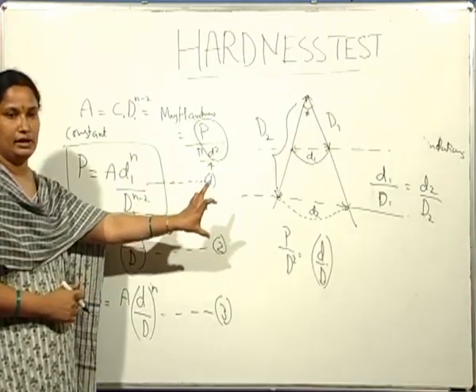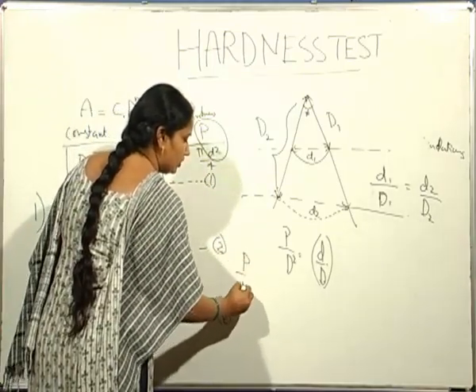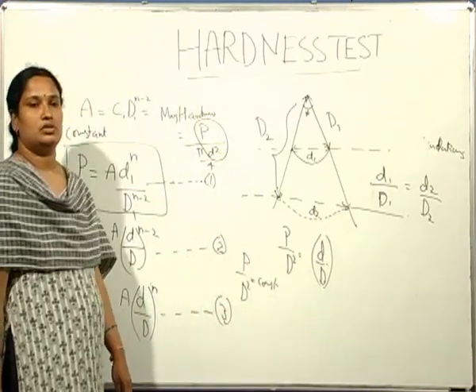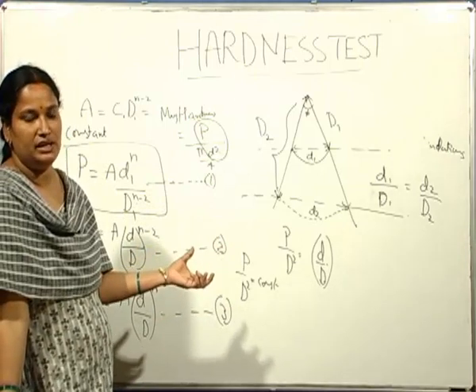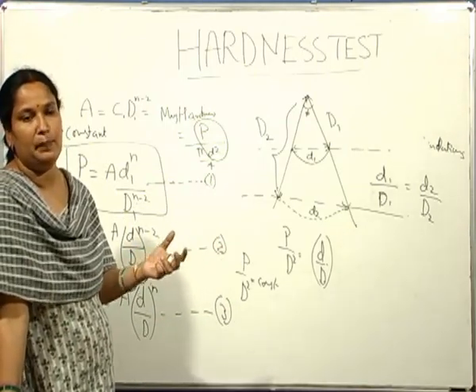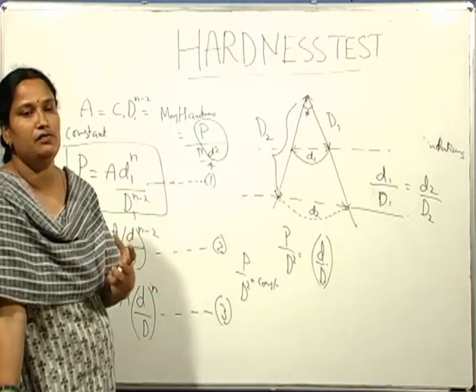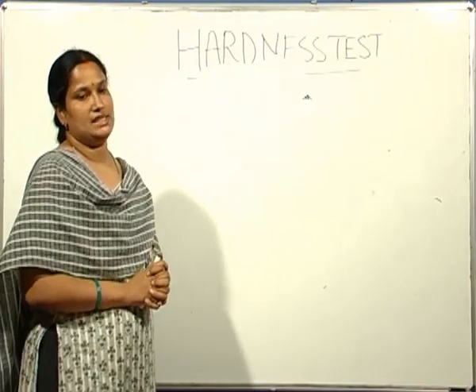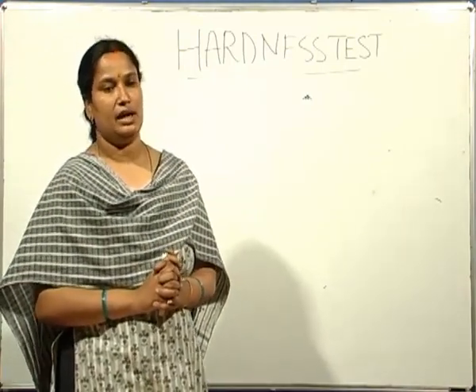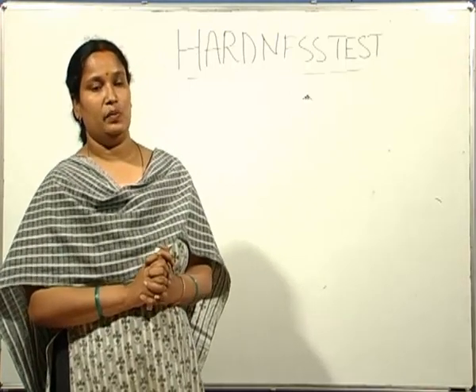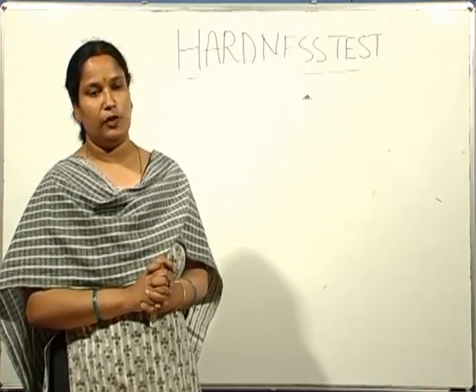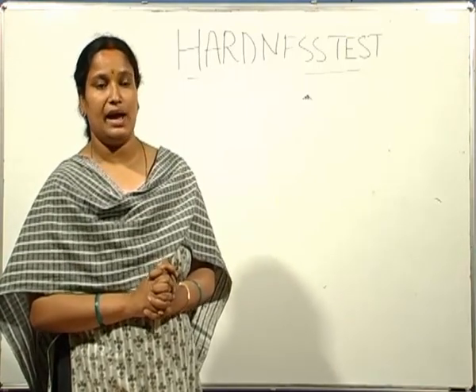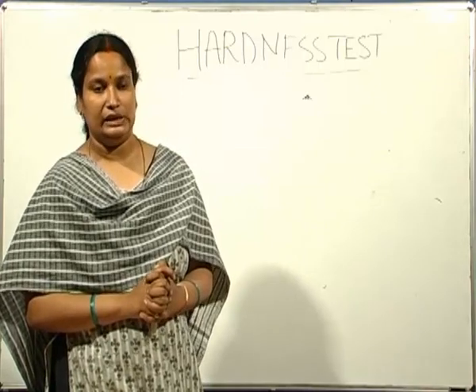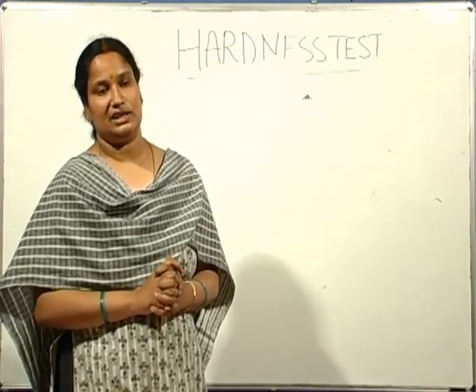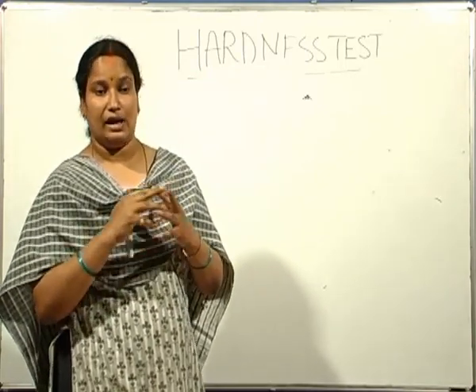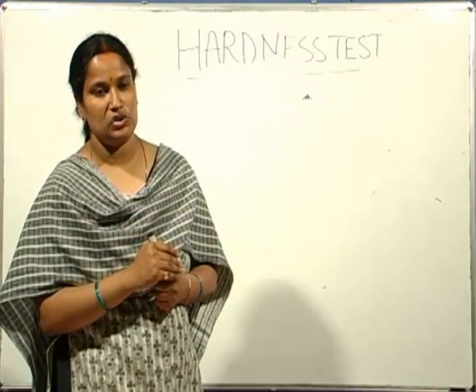So as long as the ratio P by D square is maintained constant, geometrically similar indentations are obtained and the hardness does not depend upon load. It does not vary with load. It is found that for the case of cold worked metals, Meyer hardness is independent of load, whereas the Brinell hardness is found to be constant at low loads, but as the load increases, the hardness value decreases, which shows incorrectly that as the load is increased, the material undergoes softening.